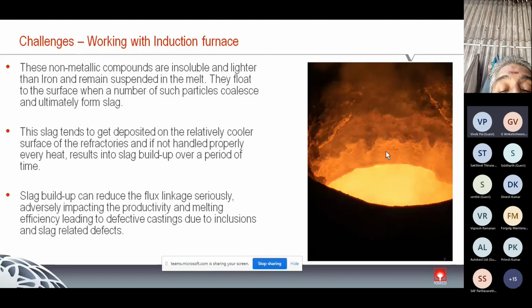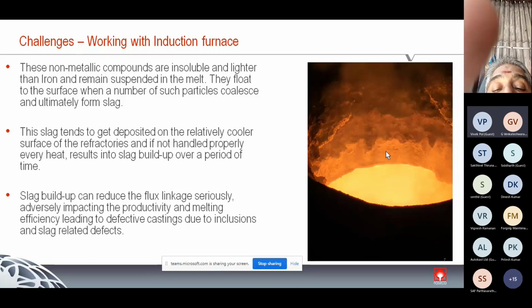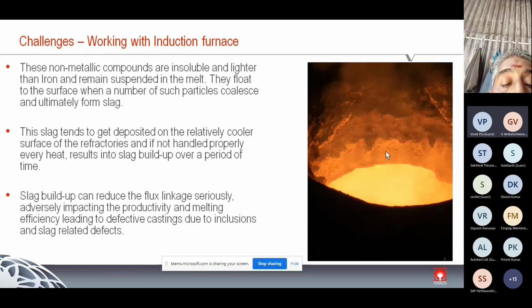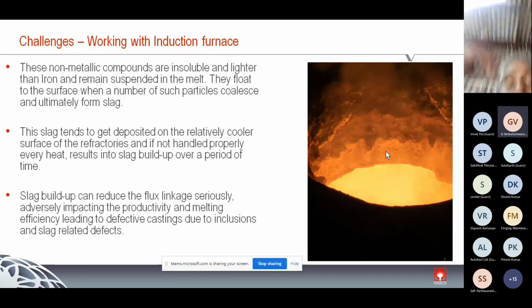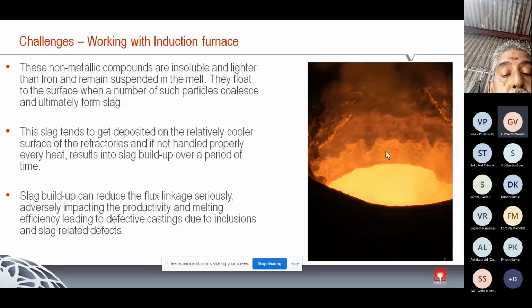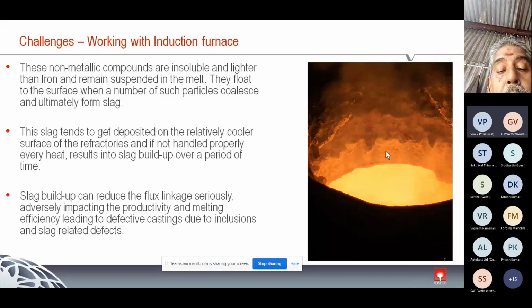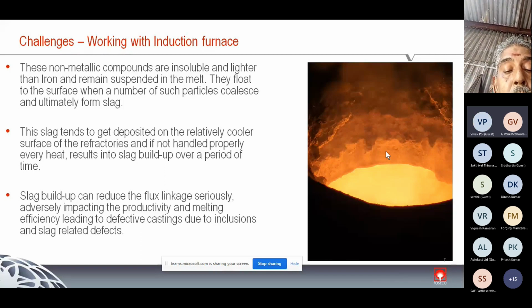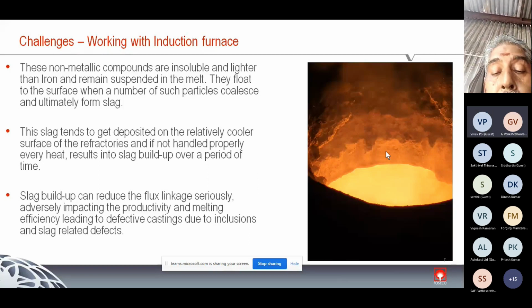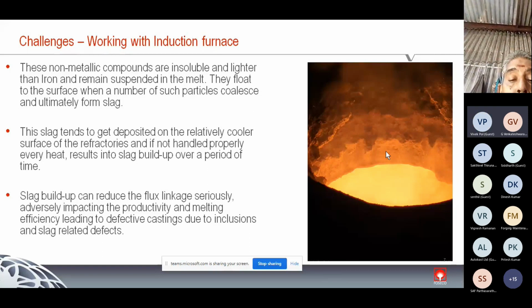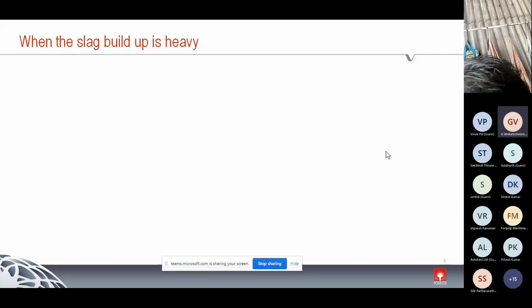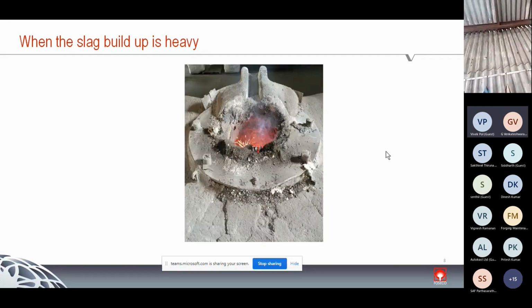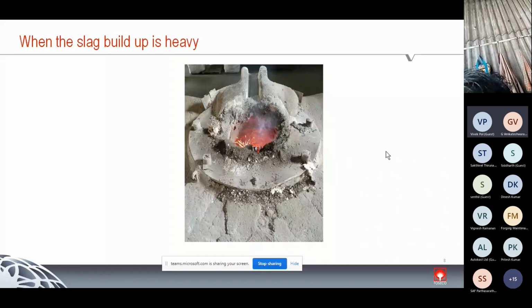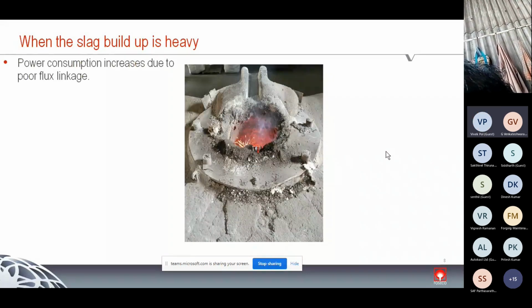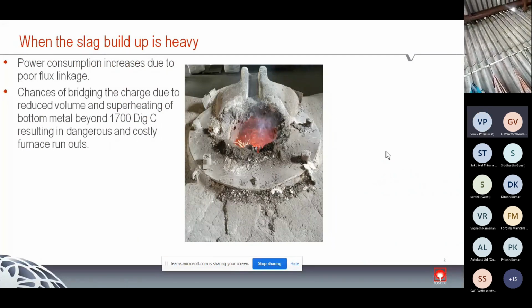The more the buildup, the more the actual furnace lining thickness increases because of the slag buildup, which reduces the flux linkage, and then the furnace will draw more power for melting. Also, there are very high chances that whatever deposition is there will go into the casting through metal transfer. If slagging is not done properly, there are high chances the casting will also get contaminated. So when slag buildup is heavy, apart from power consumption, which is definitely going to increase because of poor flux linkage, these are the challenges.